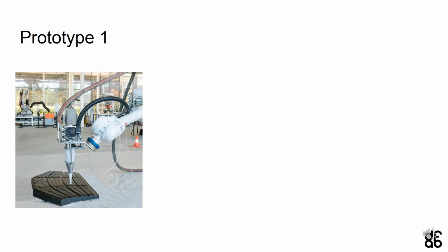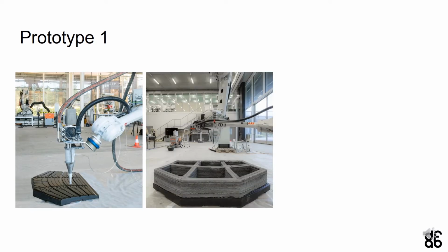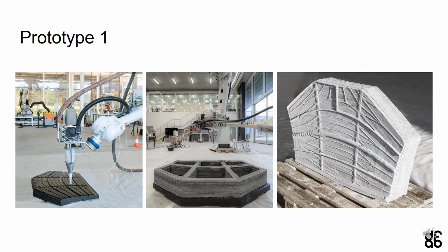We tested our approach in a series of 3 prototypes. The first one used a single piece of formwork. Here, the concrete has a similar hardening rate for the soffit as well as for the ribs, and the print path was created as a generic pattern formed by parallel lines that cover the entire surface.